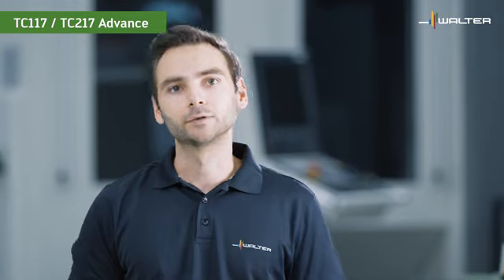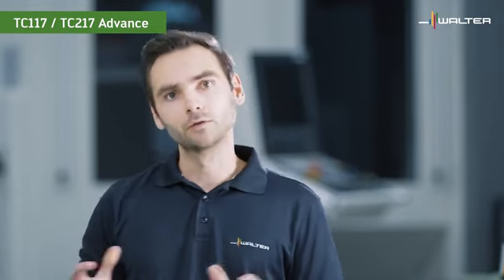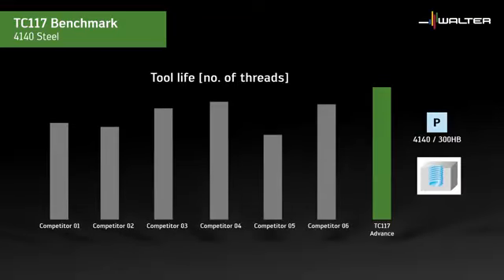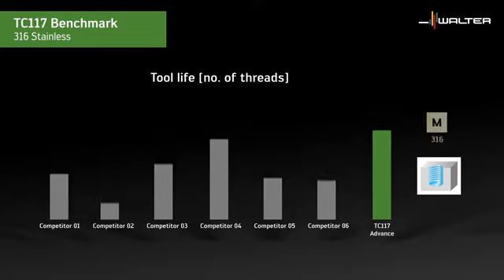It was our target to develop a universal tool that not only works in all kinds of materials, but has a great performance across the board. So here's the result of our benchmark test for the TC117 in 4140 steel with 300 HB. We have tested quite a few competitors, and in steel there is no substantial difference. But if we look at the benchmark test for 316 stainless, then the picture changes. While the performance of most of the competitors drops, the performance of the TC117 remains on a great level.